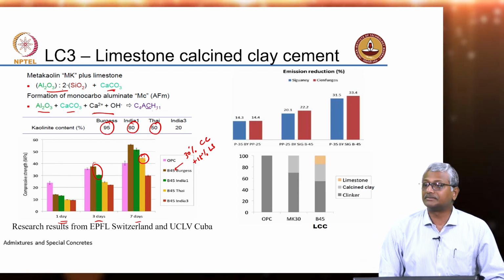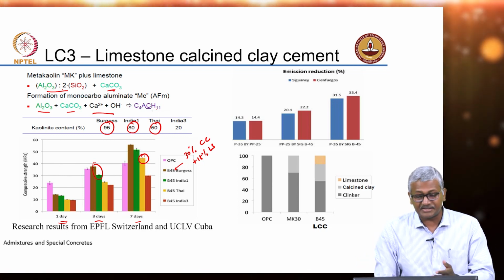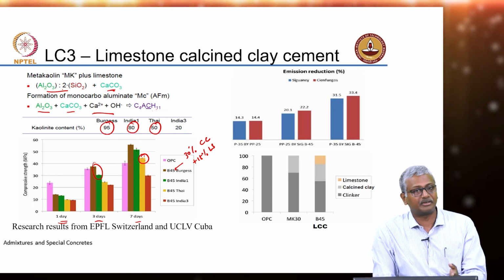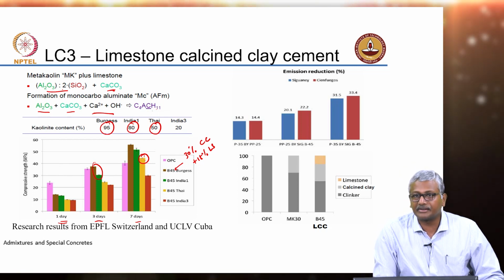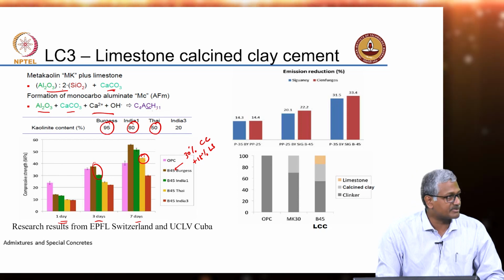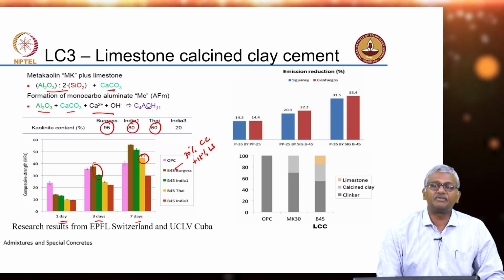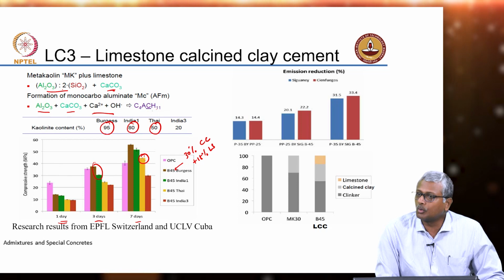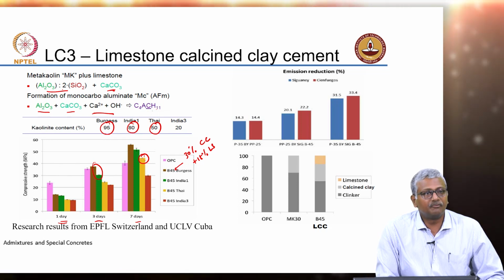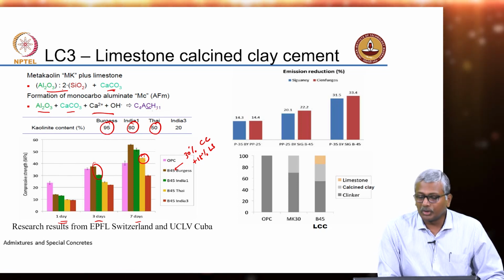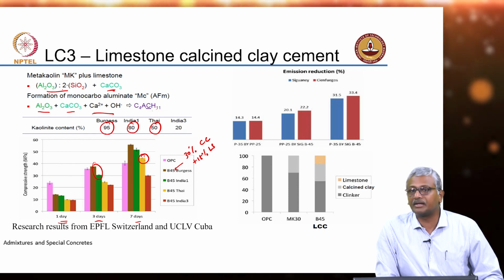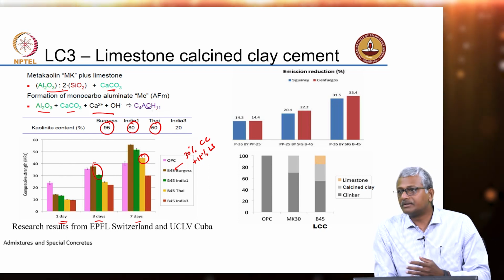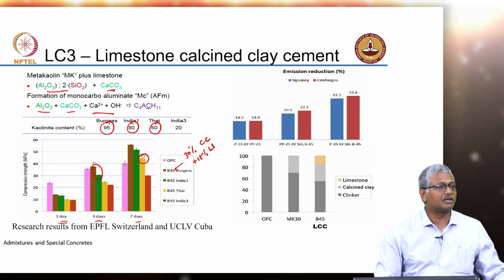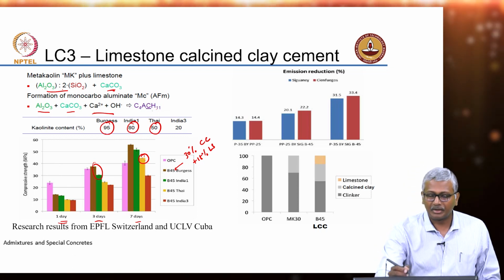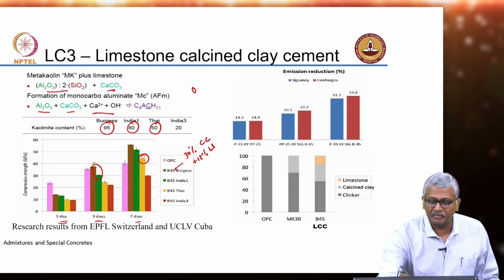So, that is the advantage here. We are replacing 45% of the cement and putting in this calcined clay limestone combination, but we are able to get a strength performance at 7 days even with an impure calcined clay. We do not have to rely on metakaolin anymore. We can go for an impure calcined clay. If you go to any of these China clay quarries where they are looking for the white China clay, there is tons and tons of overburden material which is not getting used.